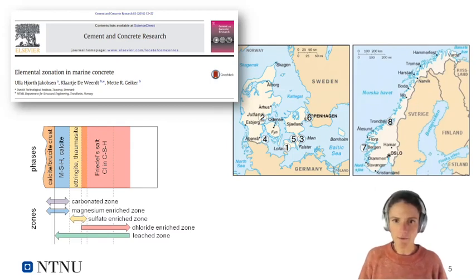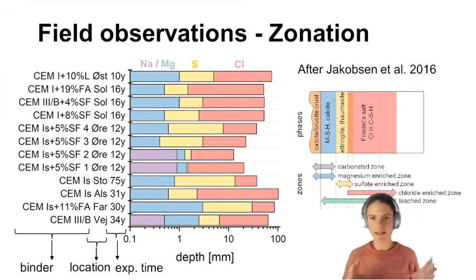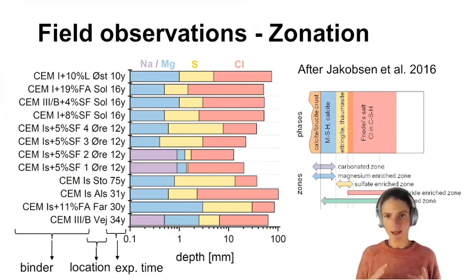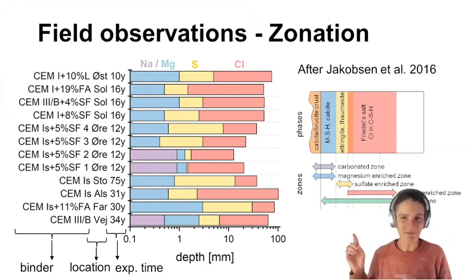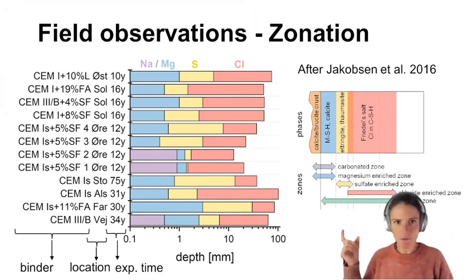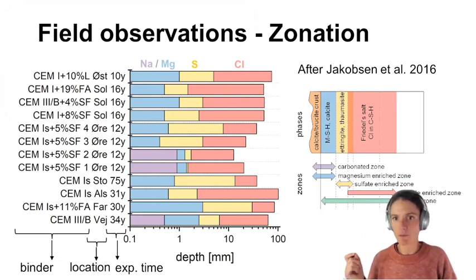And the following figure, just a selection of concretes we've looked at, illustrates how general this elemental zonation is. There are long names for the samples. The first part refers to the binder, so we had different cement compositions. The second part is the location, from different locations in Norway and Denmark. And we also had different exposure times. Some were exposed for only 10 years, whereas others were exposed for up to 75 years.